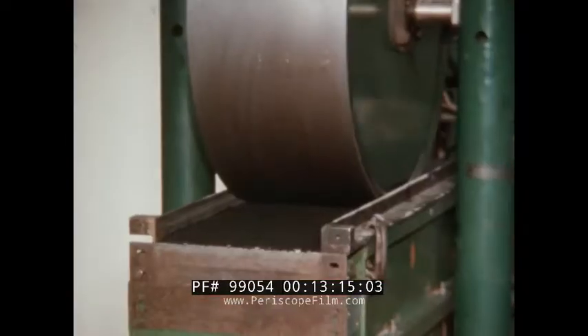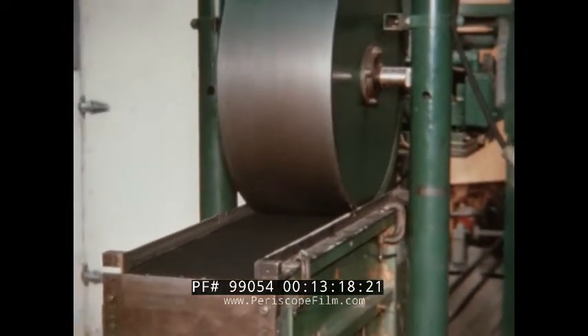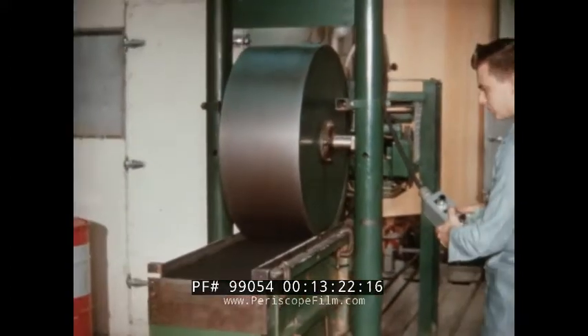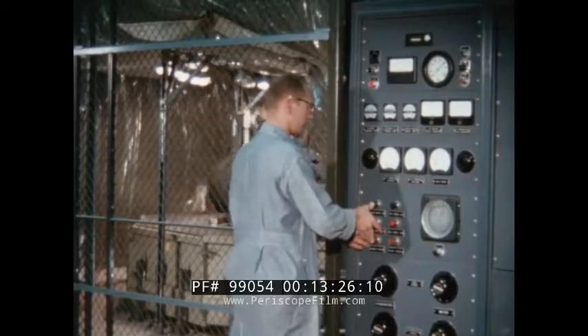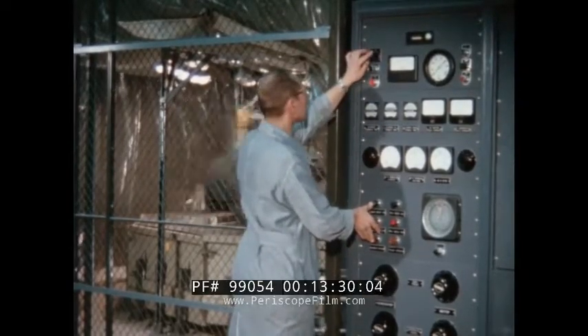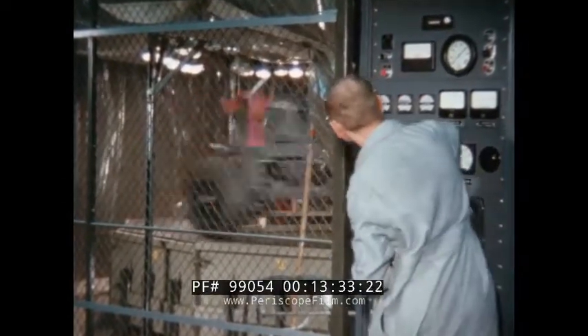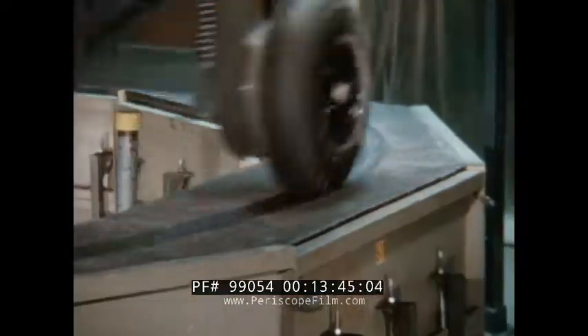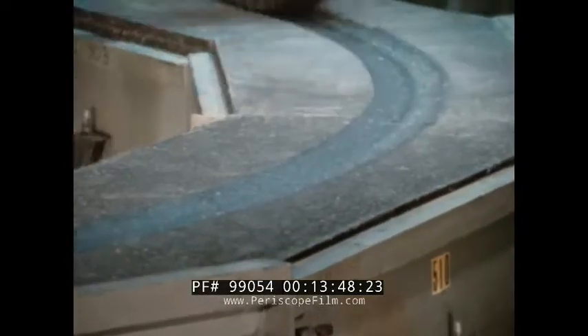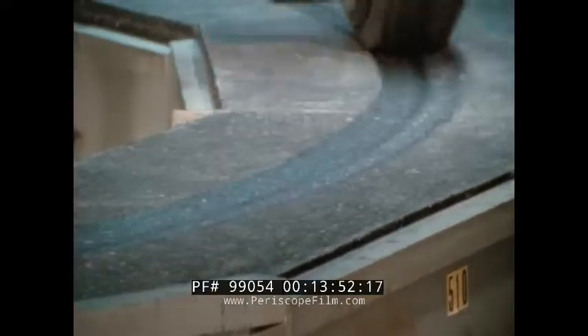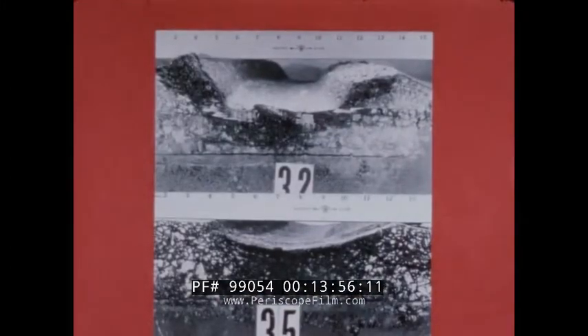One of the most interesting experiments on mineral admixtures that has been conducted was a study undertaken by the American Oil Company. Sections of paving using various mineral admixtures were made under laboratory control, then mounted on this full-scale traffic simulator to test the dynamic load strain properties of flexible pavements. The full spectrum of highway stress conditions were created, including varied temperatures, tire pressure, and wheel coverage. Under very heavy traffic conditions, asphalt content was increased up to 50% above the standard optimum value. Only the asbestos admixture safely stood up to the 50% increase in asphalt.